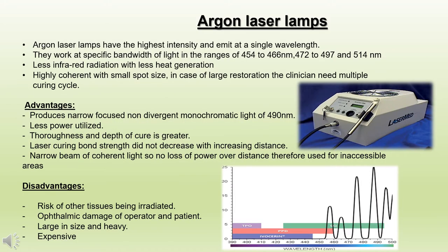Argon laser lamps have the highest intensity and emit at a single wavelength. They work at specific bandwidths of light in the ranges of 454 to 466 nanometers, 472 to 497, and 514 nanometers. Less infrared radiation with less heat generation. Light is highly coherent with small spot size.